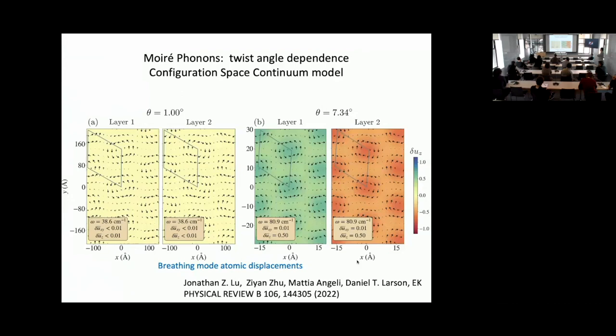Precisely because of this, I didn't have time to describe it in more detail. Several of the phonon modes are exactly localized, and they have this kind of rotational twist character, localized where these states are. So I would expect that there are indications here of very strong electron-phonon coupling. I'm not sure if that will really drive the many-body character of the system, but it's really worth exploring, and hopefully we'll have results for this soon. Yeah, absolutely, very good point.